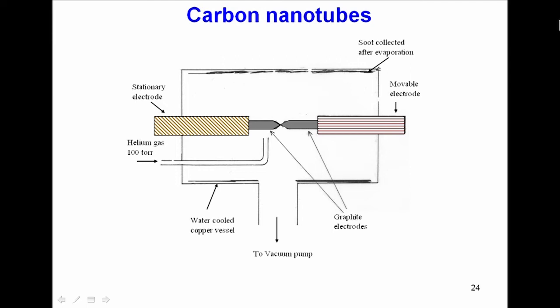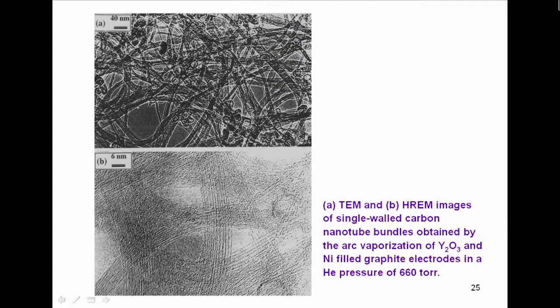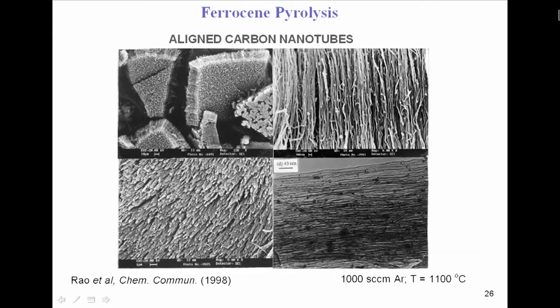And these carbon nanotubes were made by arc evaporation of graphite electrodes. What I show on top are multi-walled nanotubes. The ones in the bottom you see are bundles of single-walled nanotubes. Single-walled nanotubes are very fine capillaries, 1 to 2 nanometers in diameter generally, or 1 to 5 nanometers, with no graphitic layers on them, and you can make them all in the laboratory. And here is something where you have millions of nanotubes aligned in a particular way.